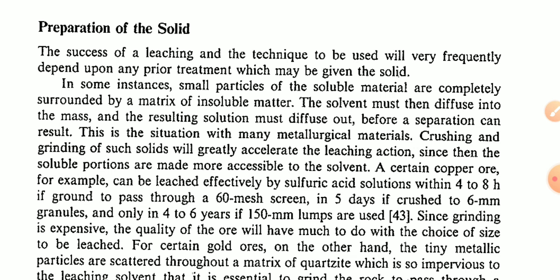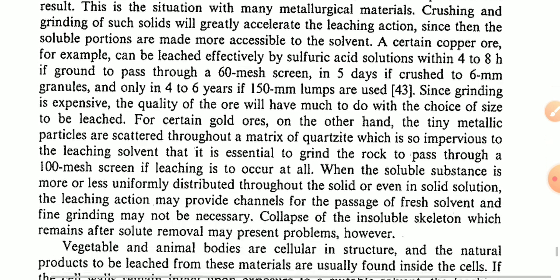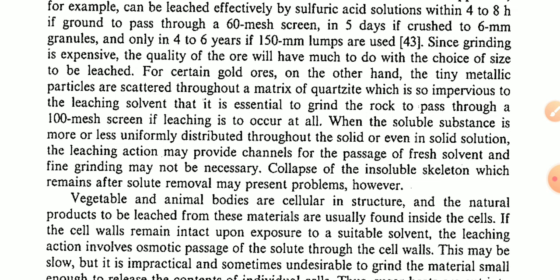A certain copper ore, for example, can be leached effectively by sulfuric acid solution within four to eight hours if ground to pass through a 60-mesh screen; in 5 days if crushed to 6 mm granules; and only four to six years if 150 mm lumps are used. Since grinding is expensive, the quality of the ore will have much to do with the choice of size to be leached. For certain gold ores, on the other hand, tiny metallic particles are scattered throughout a matrix which is so impervious to the leaching solvent that it is essential to grind the rock to pass through a 100-mesh screen if leaching is to occur at all.